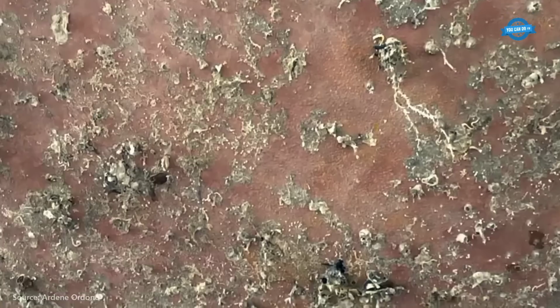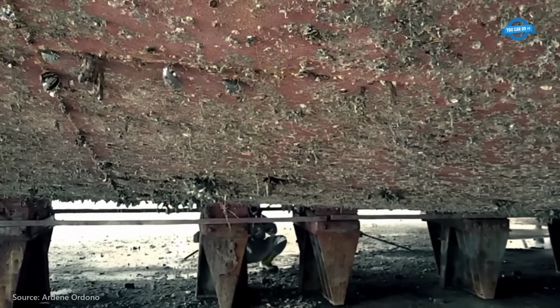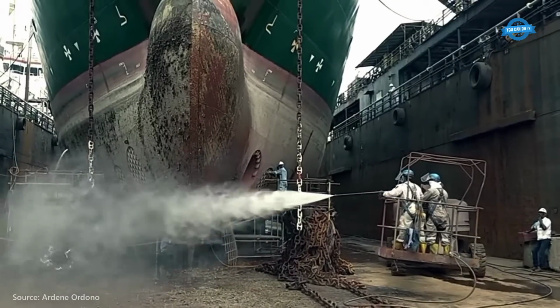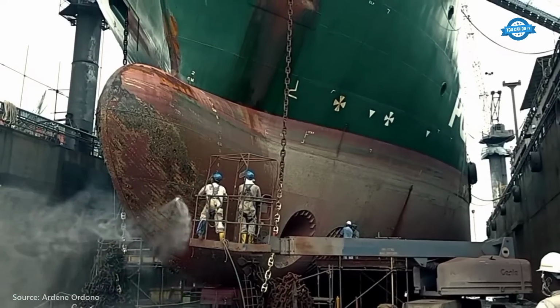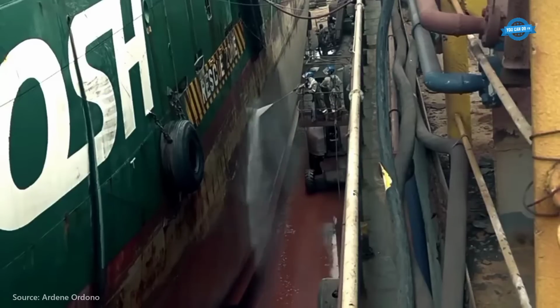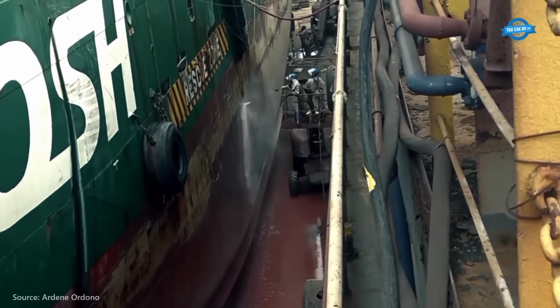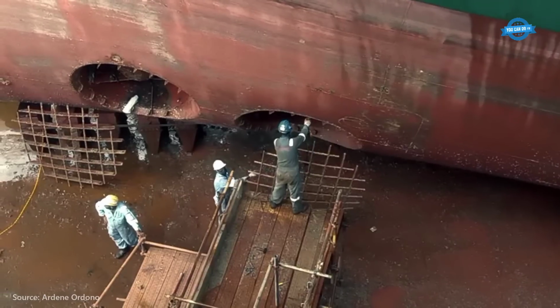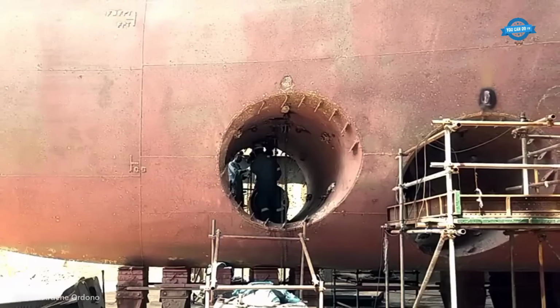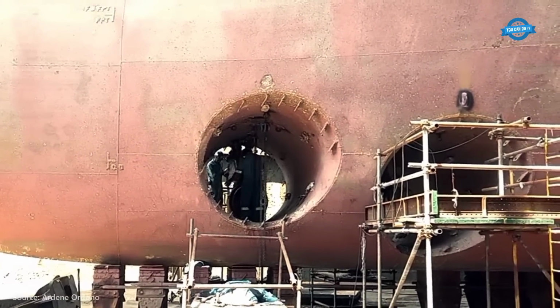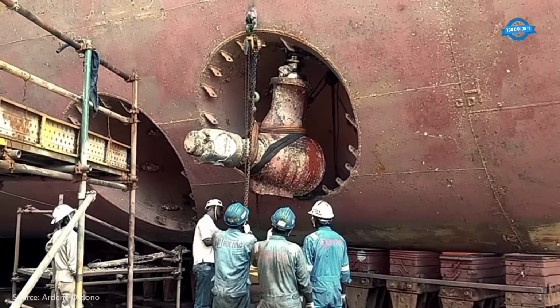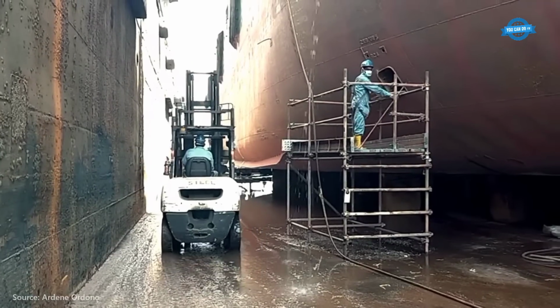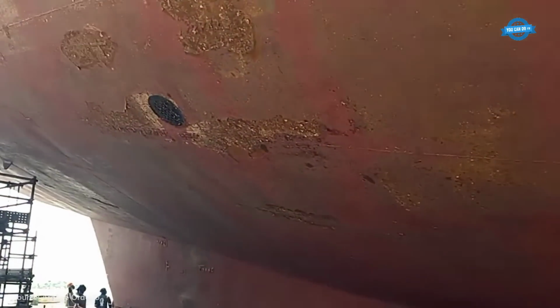Once dry, the hull is cleaned using high-pressure water jets up to 2,500 bars, removing biofouling and old coatings across an area that can exceed 10,000 square meters. Non-destructive testing methods like ultrasonic thickness measurements and magnetic particle inspection identify structural degradation. If hull steel is reduced by more than 25%, replacement is mandatory.